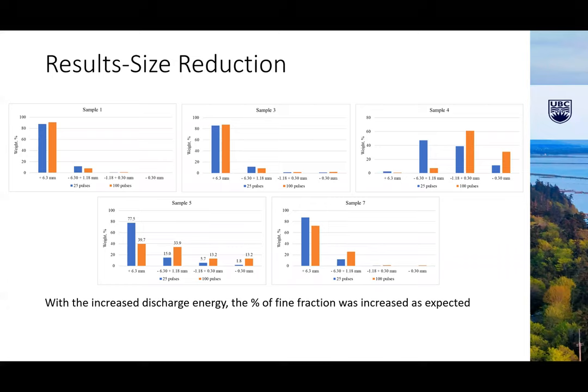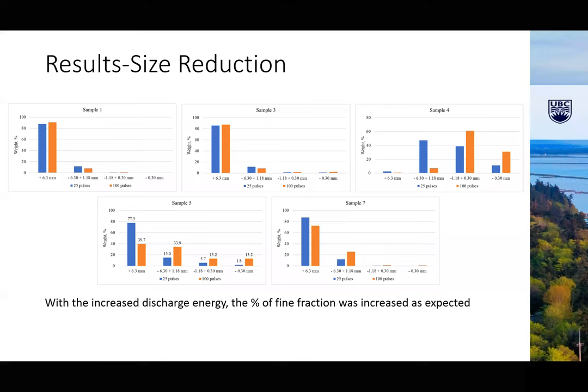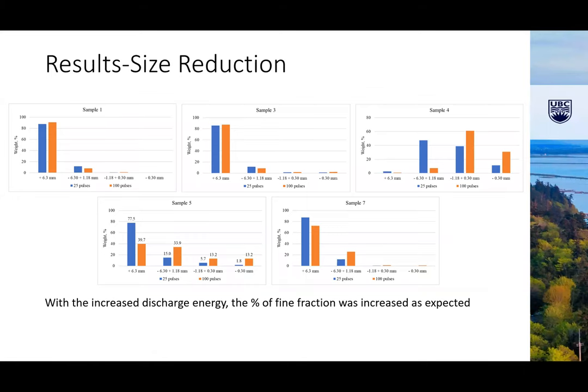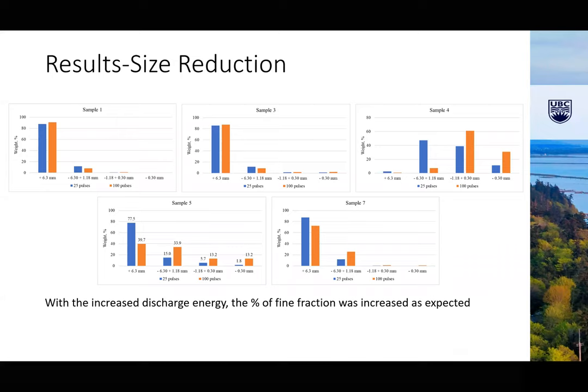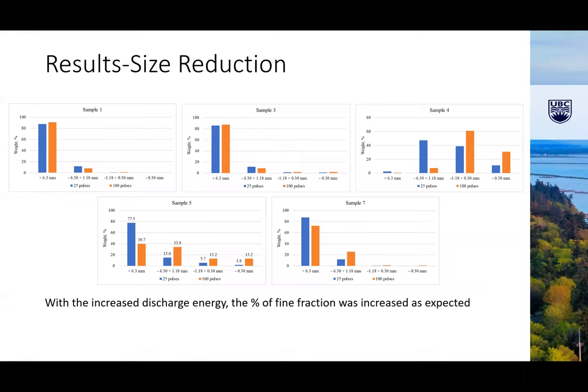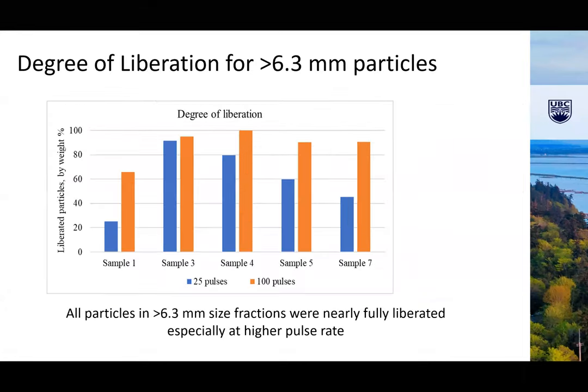Actually, it was true that with increased discharge energy, the fine fraction was increased in most of the cases, however, not significantly. So we have bars for the 25 and 100 pulses. And well, definitely the coarser fractions are still significant for some types of lamps. So that means it did not generate a lot of fines.